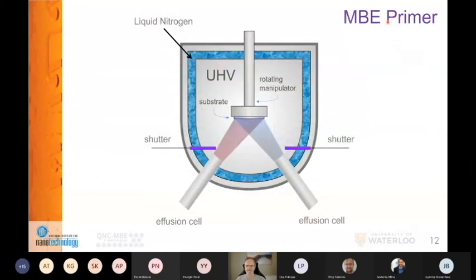So this is now a quick MBE primer. This is where the action is happening for us. We have ultra high vacuum and effusion cells with ultra clean elements, and we have shutters which can close the beam off and open it up so we can supply the elements on demand. In principle, those shutters work very well, stopping the beams almost instantaneously and letting them in. However, one element, specifically arsenic, is not particularly keen to stick around, and it bounces, and even when you put the shutter in, you still have some arsenic behind, which creates challenges to grow very abrupt interfaces where you don't want arsenic beyond indium arsenide.